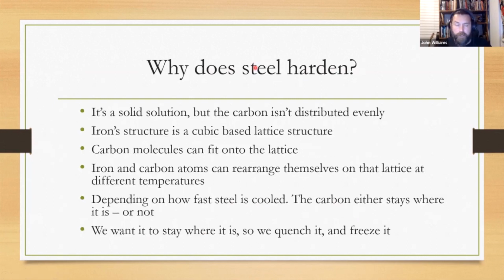Why does steel harden? Steel hardens because, as Victoria mentioned earlier, let's back up to what you would call the baseline state with steel. If you just let it cool gradually, it's going to form what's called pearlite, and that's soft. That's what's happening when you normalize something. When you anneal something, you bring it up to temperature, you let it cool down slowly, and it's soft and stress-free. It has carbon in there, but it's not distributed very evenly. Mostly you have the ferrite, that's the soft stuff, and then this other stuff called cementite, and mostly the carbon is tied up in that cementite.